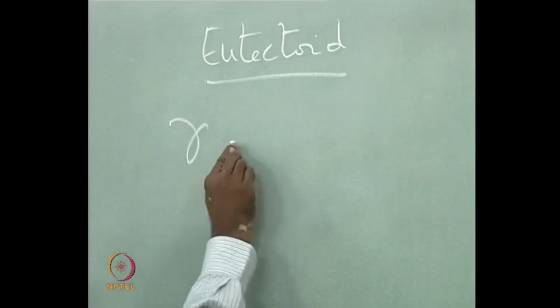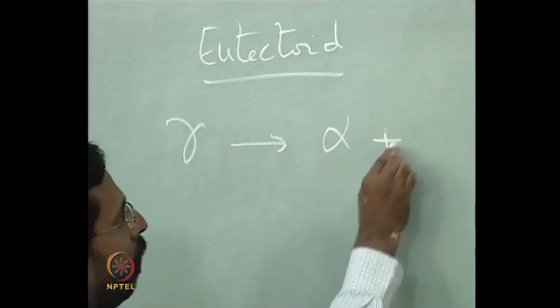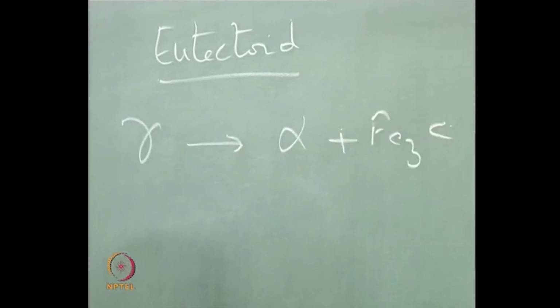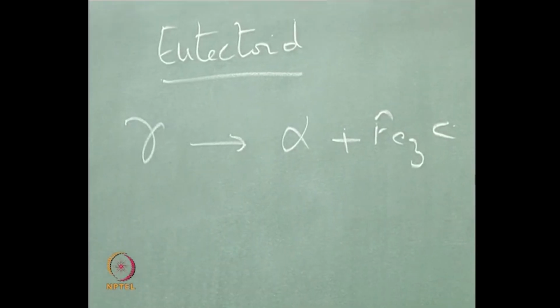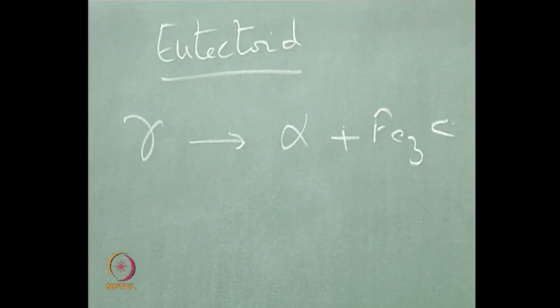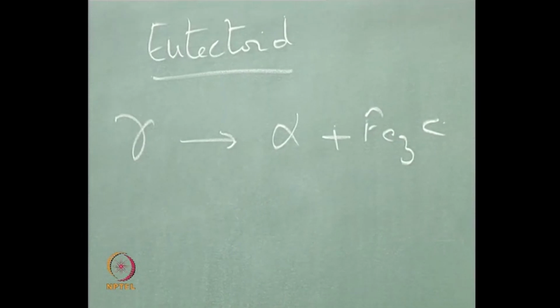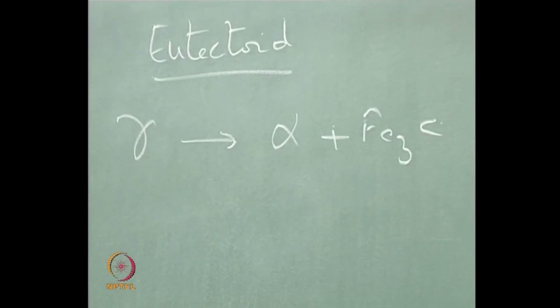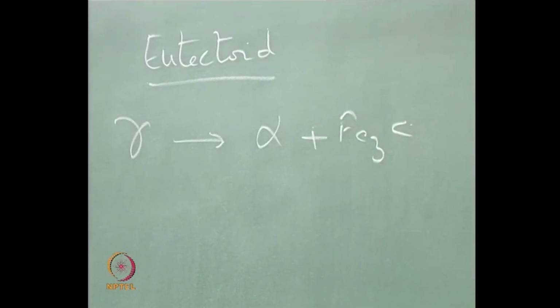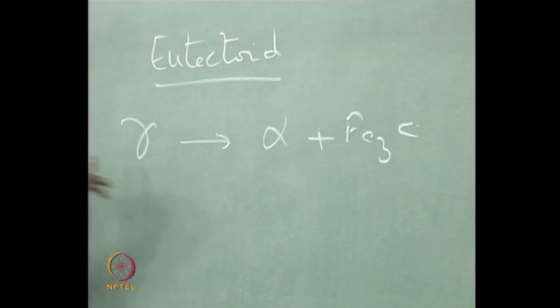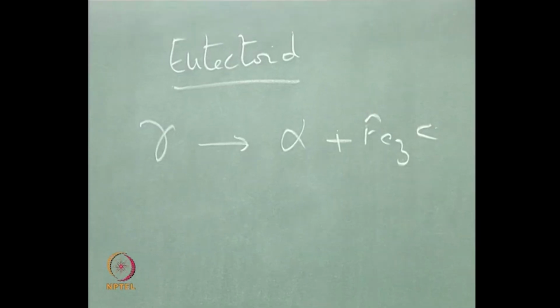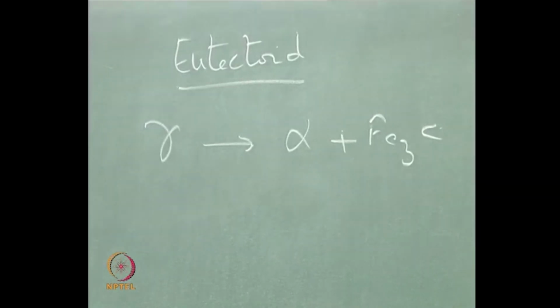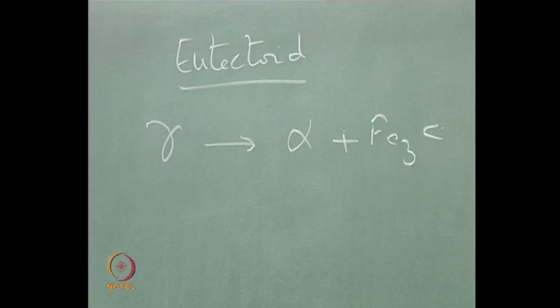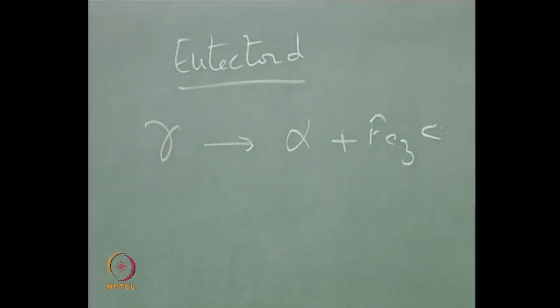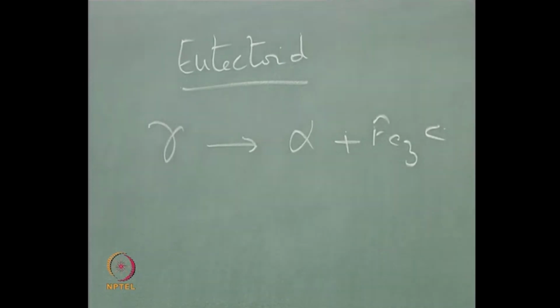Good. Okay. So it is austenite, which is referred to as gamma, transforms to ferrite, which is referred to as alpha, plus cementite. This is what we see, and in general her statement is right that one solid gives you two solids, and that is what a eutectoid transformation is. And this transformation, if you carefully observe, in comparison to the precipitation, in precipitation you have a matrix from which a precipitate is coming out, and this precipitate has either a different structure or the same structure.